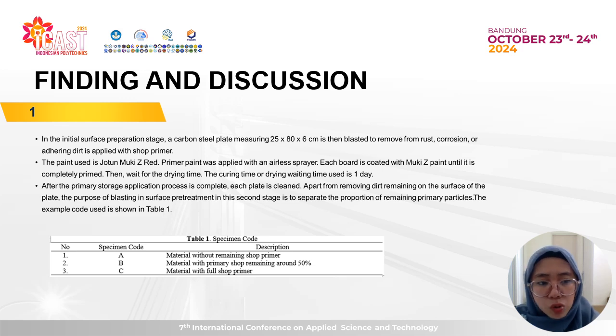After the experiment process, in the initial surface preparation stage, a carbon steel plate measuring 25 times 80 times 6 centimeters is cleaned to remove rust, corrosion, or other dirt. It is then applied with shop primer. The paint used is Jotun Muki-Z. Primer paint was applied with an airless sprayer. Each part is coated with Muki-Z paint until it is completely primed. Then wait for the drying time. The curing or drying time used is 1 day.